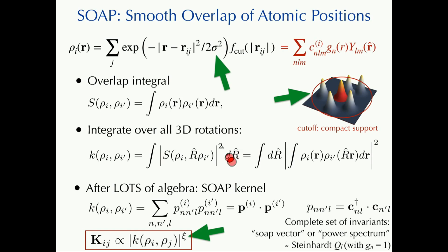So the three that are here on this slide are this atom sigma, so the smearing of the atoms, the cutoff, and that cutoff has to be part of any interatomic potential, and this exponent, which essentially is 2. So very, very few parameters. The sigma is basically 1 Bohr, because it's the size of each atom. We don't really change it. So essentially, there are very few parameters. They're all set from physical considerations, and the kernel then is defined and is always the same.